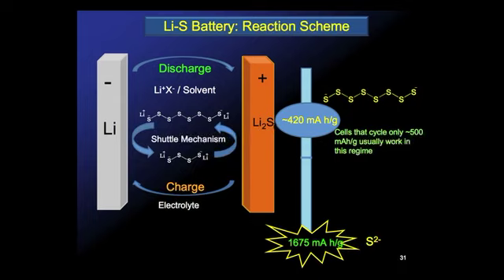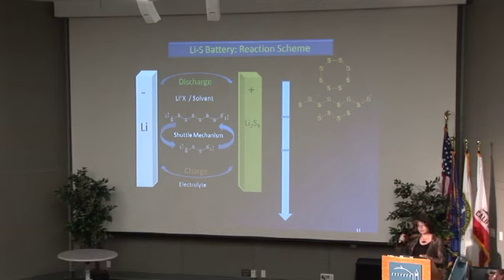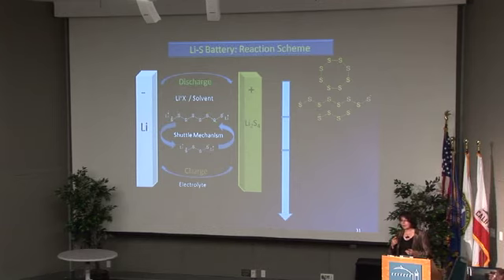If you continue to reduce, you sometimes enforce what's called a shuttle mechanism. Because of the solubility of these sulfides, they diffuse out into the electrolyte. And they will engage in a sequence of redox reactions where the more reduced species is sequentially reduced and oxidized within the electrolyte. So effectively, this transports over to the negative electrode and back to the positive electrode. This little shuttle mechanism operates within the electrolyte. It actually serves as a safety mechanism, but it also reduces the efficiency of the cell dramatically.